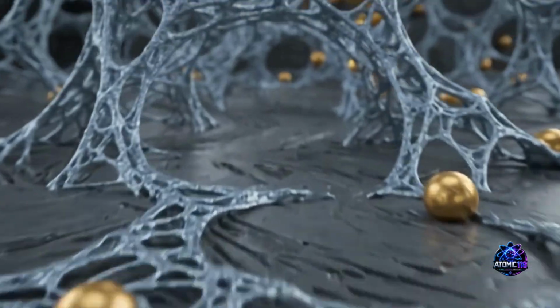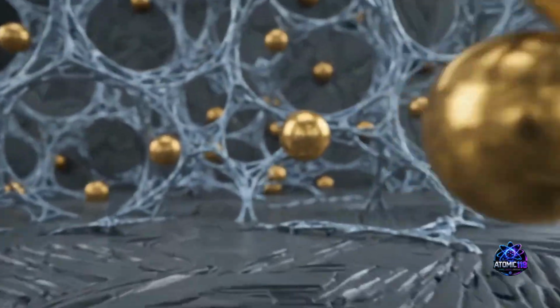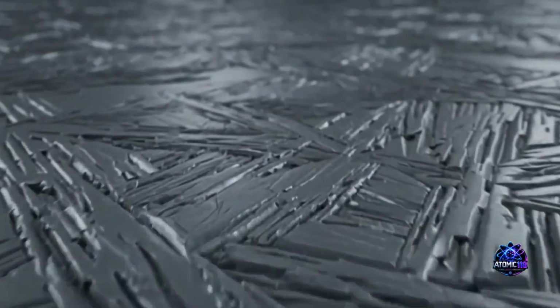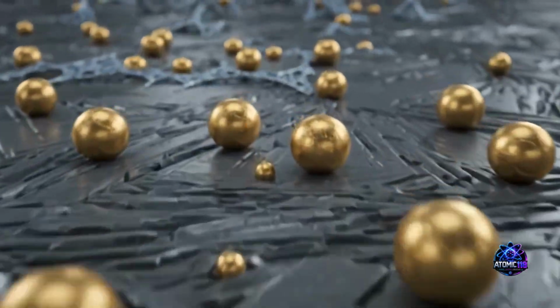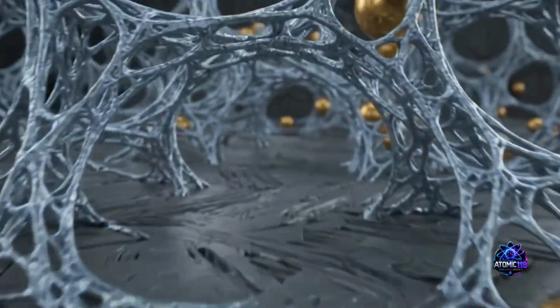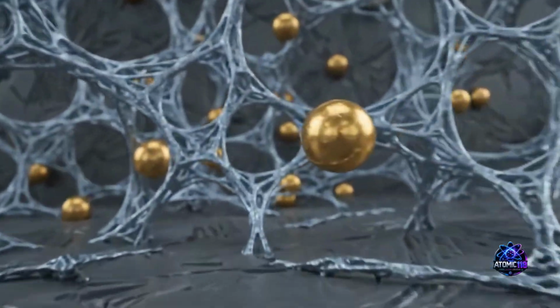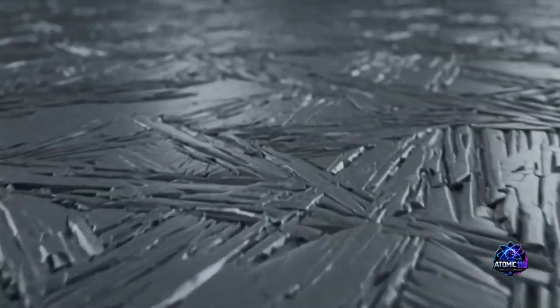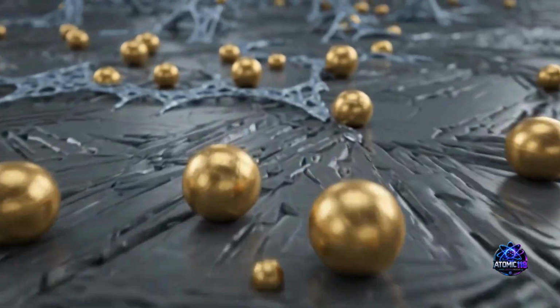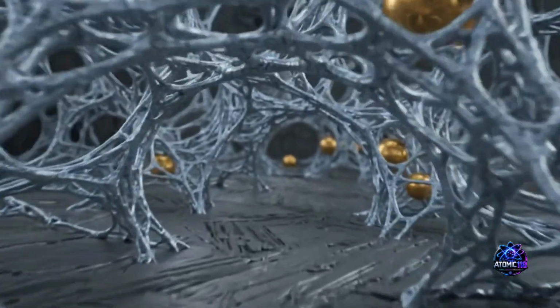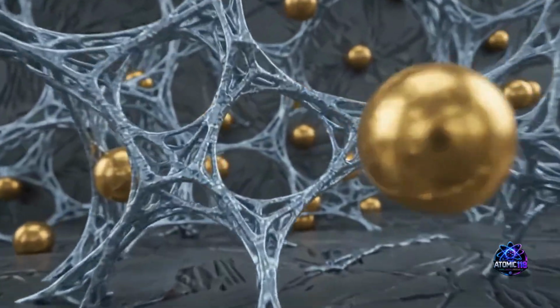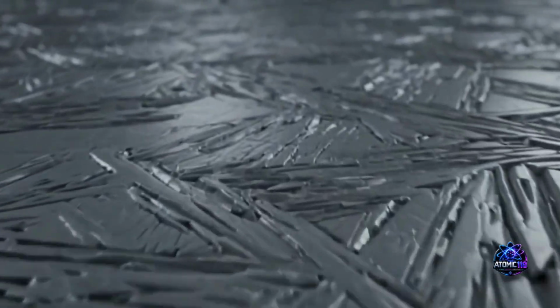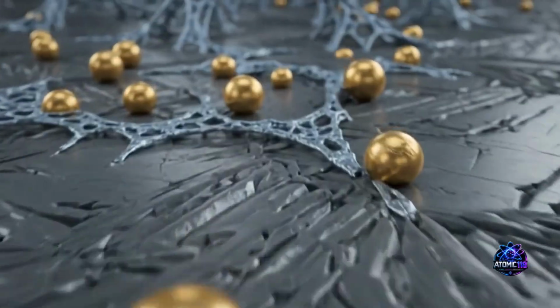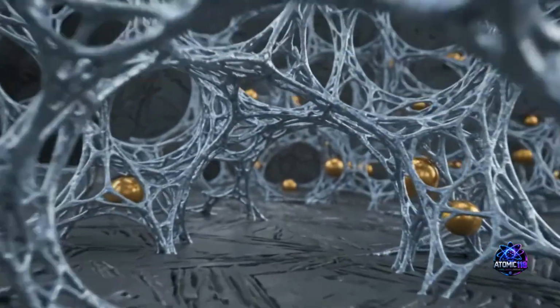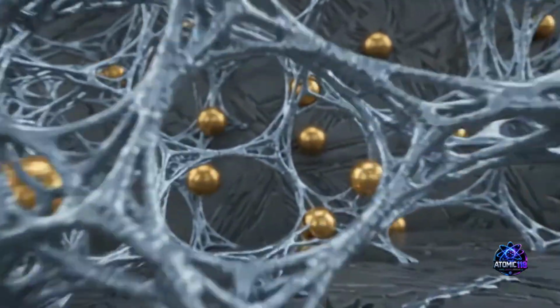But if we move away from the turbines and down to the mechanical extremes, I'm going to argue for Team Vanadium. All right, let's hear it. Because chromium-vanadium steel thrives in environments of catastrophic physical abuse. Because of those ultra-fine grains pinned by the MC carbides, CRV steel achieves a massive load-bearing capacity. An incredible shock absorption. It handles sudden, violent force better than almost anything else. Right. If you need to put a heavy steel cheater bar on a socket wrench and literally jump on it with your full body weight to snap a rusted bolt loose, you are relying entirely on vanadium. A standard steel wrench would shear in half.